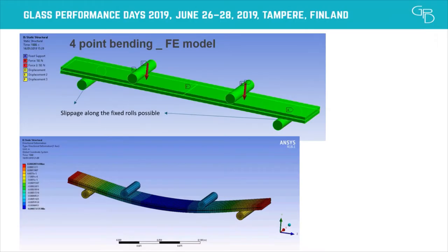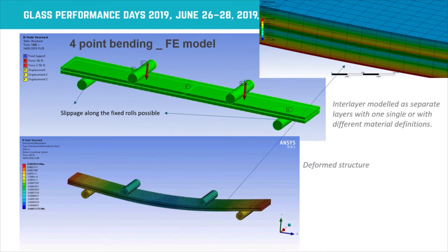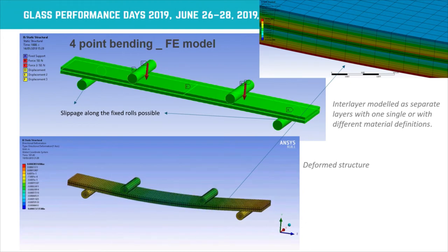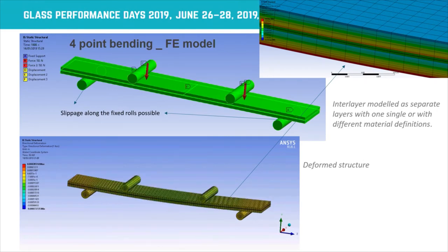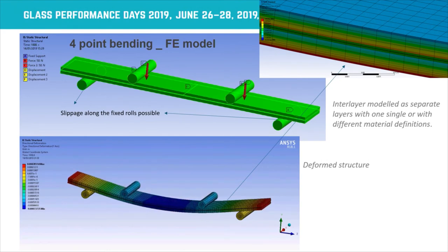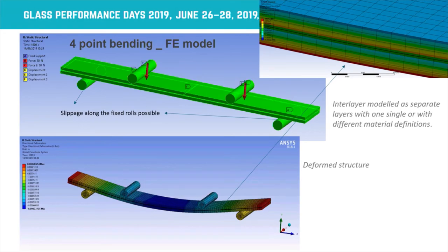We performed four-point bending experiments and built a corresponding finite element model. The standard setup applies 50 Newton force and monitors deformation over time. Meshing consists of three layers for each skin and three for the core — nine layers in total. Depending on the model used, these layers either receive identical properties based on the equivalent modulus, or different properties for skin versus core.